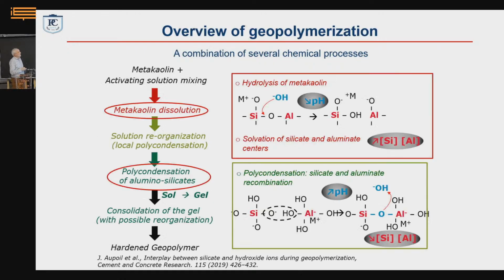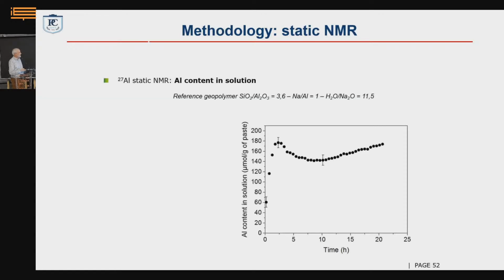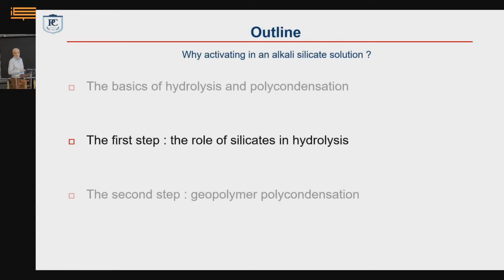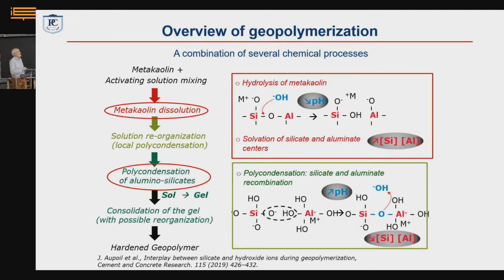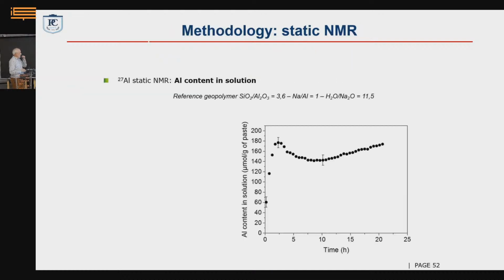So let's see what we can understand about this first process of dissolution and recondensation. And in particular, why do we need to do that with silicates? Because if you look at my scheme here, you would say, okay, I just need sodium hydroxide. But we have seen that it's very different with silicates. So what makes the presence of the silicate make this scheme different? To do that, we just follow the system by NMR, doing aluminum-27 NMR in the liquid phase.